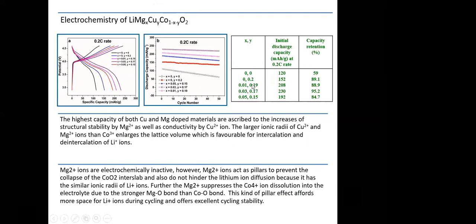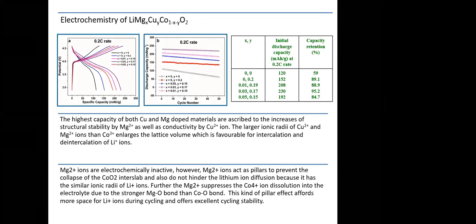Here you can see the optimization of copper and magnesium, with magnesium 0.03 mole and copper nearly 0.17, delivered 230 mAh per gram at 0.2C rate and 95.2% capacity retention. In a similar way, people are now also doing copper, magnesium, and vanadium doping in NMC, LFP, and other cathode materials to improve performance. We also incorporated magnesium in lithium iron phosphate and achieved nearly 180 watt hour per kg energy density in LFP, which otherwise delivers only 150.